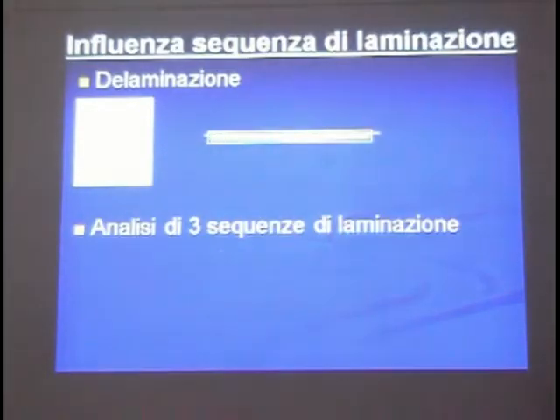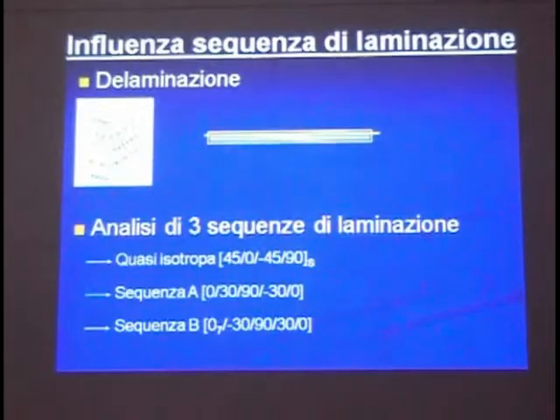I will go rapidly through this part. We have been studying delamination using 3 lamination sequences. The quasi-isotropic already shown, and then sequence A, 0, 30, 90, minus 30, 0, and the sequence B, 7 layers at 0, then minus 30, 90, 30, and 0, which are 2 stacking sequences used in the boat hull at the bottom and at the flank of the boat.